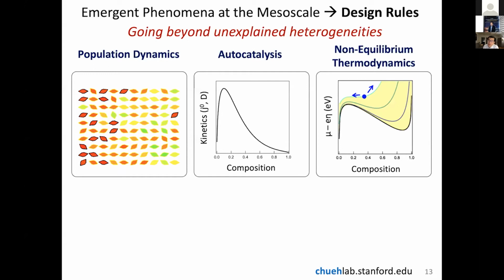The third and the final theme will be non-equilibrium thermodynamics. Many of the materials we use for batteries and other electrochemical technologies will establish phase diagrams. We know where the single phase regimes are, we know where the two phase regimes are. But the problem is that a battery operates very far from equilibrium. We're constantly applying current. We have an overpotential, which takes it away from equilibrium condition. So in order to understand the phase behavior of this material, we must understand the thermodynamic properties at non-equilibrium condition. In other words, what determines the stability of the system when the material is undergoing current flow and other electrochemical cycling.